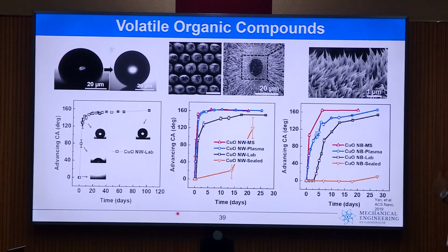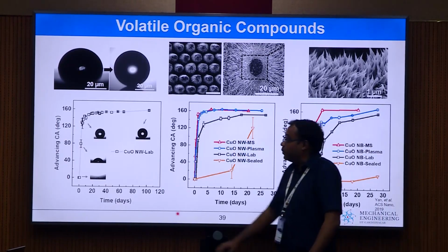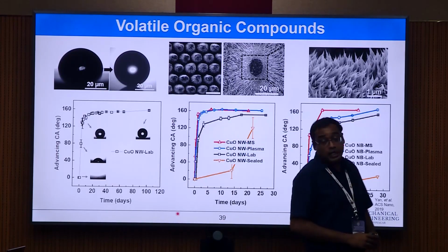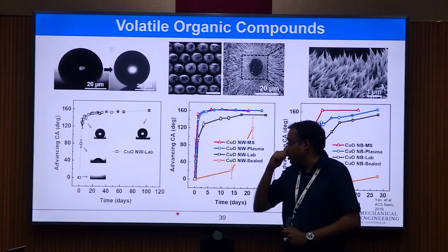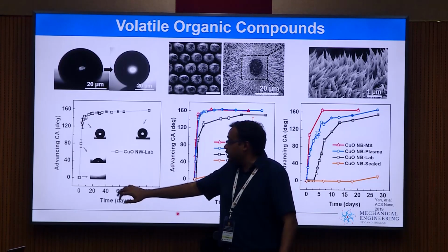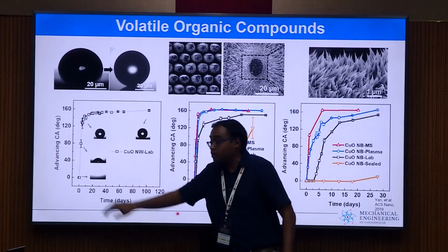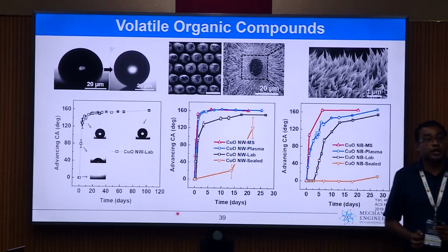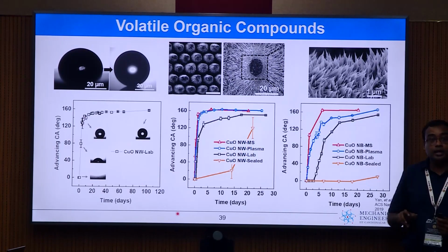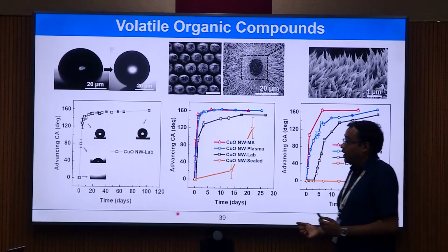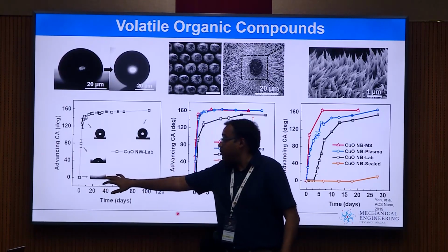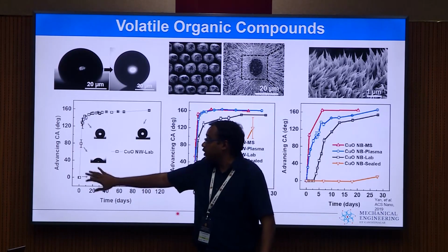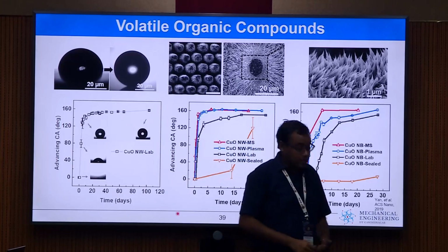Now, to further validate this, we started with a pristine bare copper, cleaned through plasma. At time equal to 0, we got a superhydrophilic surface. We left the surface in a lab environment, not in a completely airtight container, but in an open petri dish. What we found is that with respect to the number of days, the hydrophobicity of the surface increases.